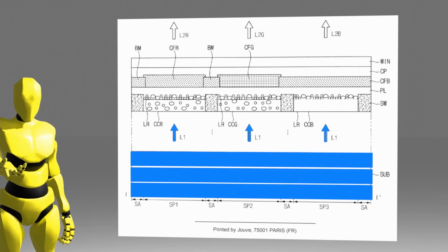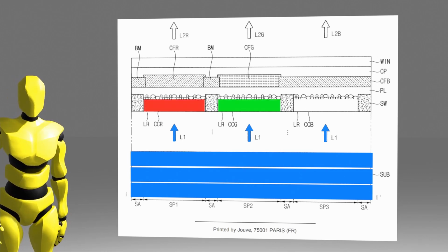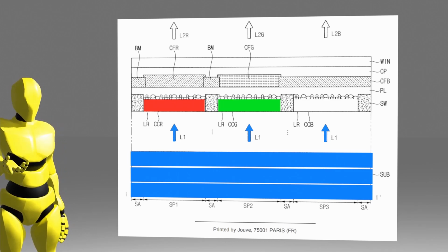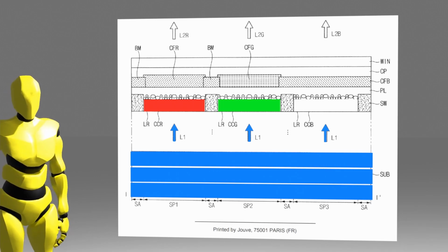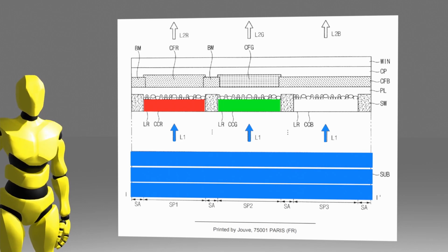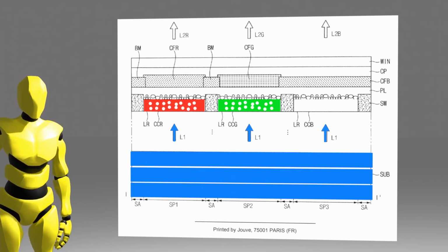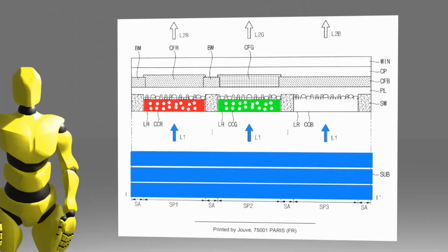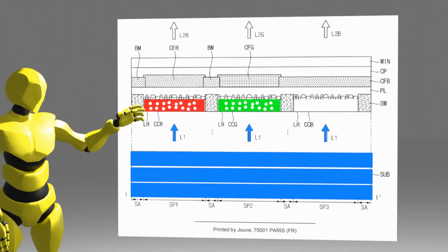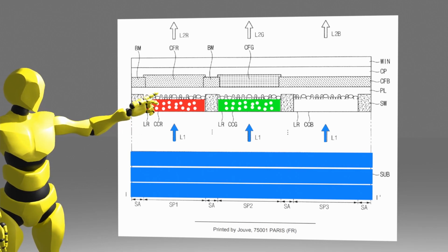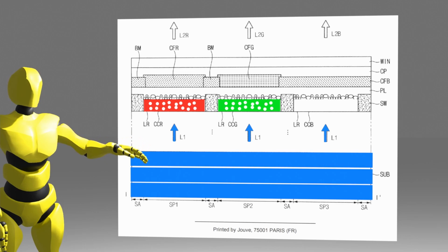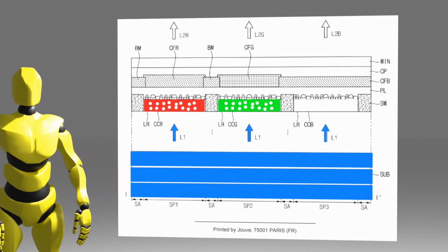The light emitted from the blue OLED has to be converted to red or green depending on the subpixel, so it meets the quantum dot layers of green and red depending on the location. And since the blue subpixel does not require color conversion, a separate quantum dot layer is not included. And the quantum dot layer contains a scattering agent that causes strong scattering, and the reason will be explained later. Light passing through the quantum dot layer meets small particles as shown in the patent drawings. These particles have a very low refractive index and selectively reflect blue. On the other hand, the transmittance for green and red is high. This will also be explained later.